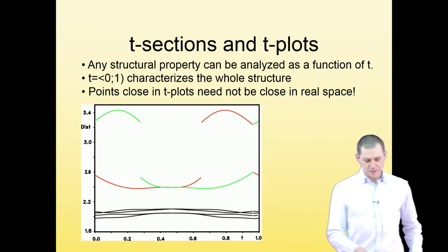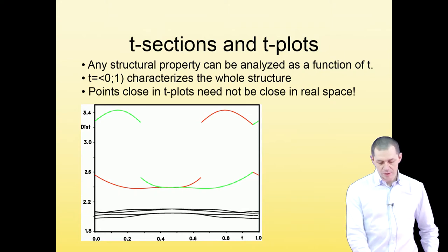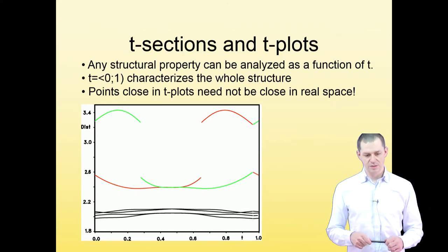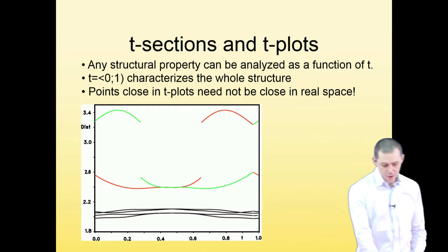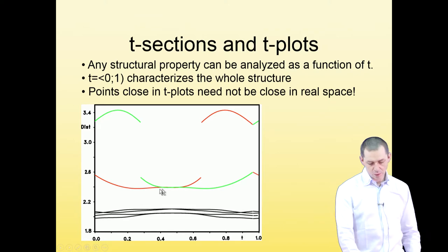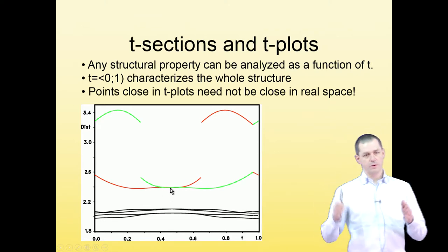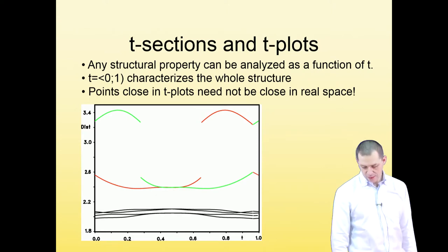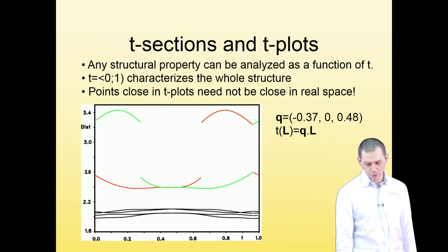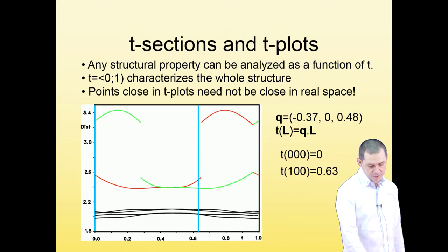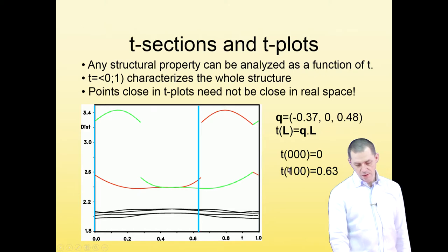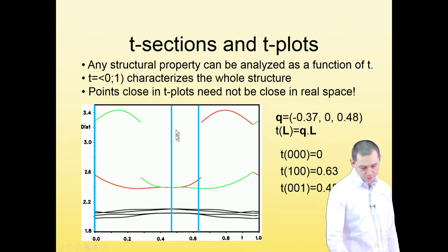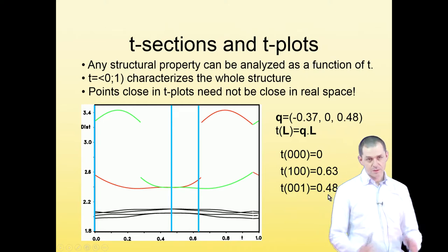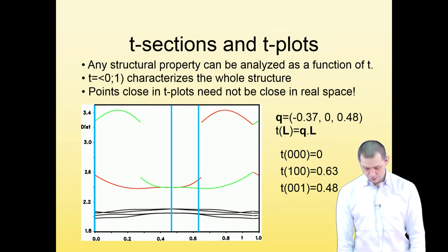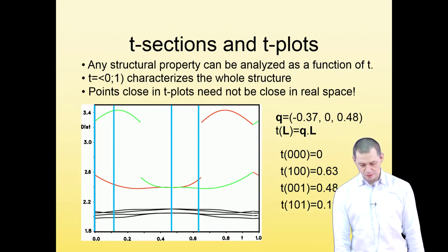What is important is that the points that are close in T-plots are not close in real space. So you can't say that there is a long block of structure which has this coordination, and then a long block of structure which has that coordination. No, neighboring unit cells are distributed in this plot in a well-defined manner, but they are not close to each other. So here are the examples. This may be the coordination in the first unit cell, and this is the coordination in one unit cell along A. This is the coordination in the neighboring unit cell along C. So this can be calculated, of course, but they are not close. The unit cells close in the structure are not close in the T-plot.